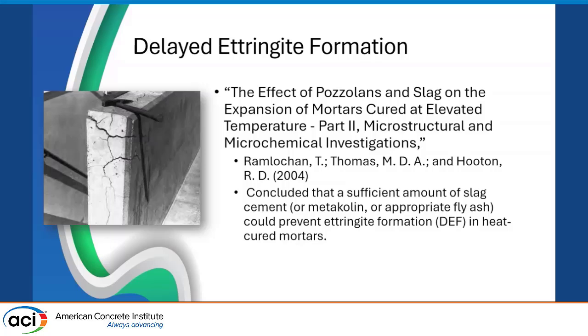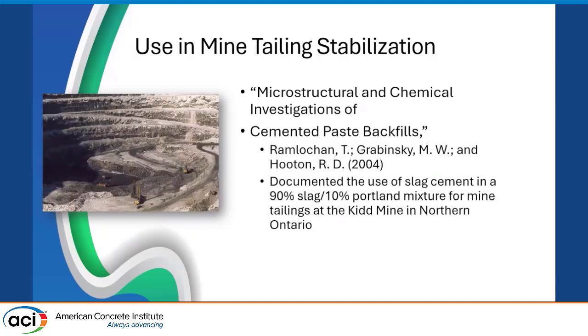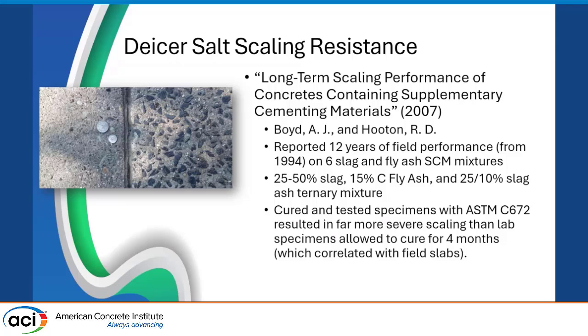On delayed ettringite formation, there was a paper called The Effect of Pozzolans and Slag on the Expansion of Mortars Cured at Elevated Temperatures: microstructural and microchemical investigations. Basically, what Doug showed here was that for slag, metakaolin, and fly ash, using the right materials and the right amounts, you could generally prevent DEF from occurring in heat-cured mortars. Even outside the box of concrete, he had a paper called Microstructural and Chemical Investigations of Cement Paste Backfills, which looked at a particular mine, the Kidd Mine in northern Ontario, where they used 90% slag and 10% Portland to stabilize the mine tailings.